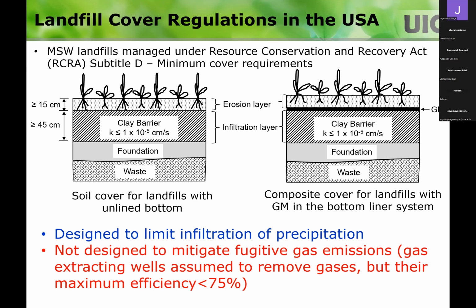They assumed that gas extraction wells will take out all the gases. But there is overwhelming data that shows that gas extraction wells that you have at the sites, at most their efficiency is 75%. So it's less than 75%. So you have 25% of the gases that are going to be fugitive gases. And if that extraction well system is not designed well, it could be much, much higher, right?